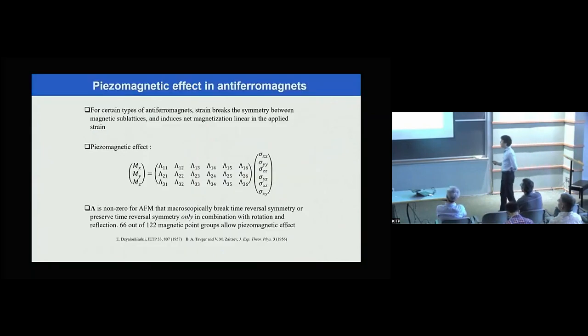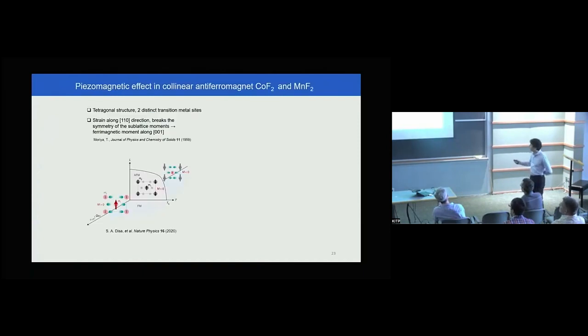So here comes the piezomagnetic effect. For a certain type of antiferromagnet, the strain breaks the symmetry between magnetic sublattices and induces a net magnetization linear in the applied strain. I describe it in this form. And this lambda tensor is only available when the material breaks time reversal symmetry, or preserves time reversal only in combination with rotation and reflection. So this has a long history of research. For example, cobalt fluoride, manganese fluoride, 1950s.